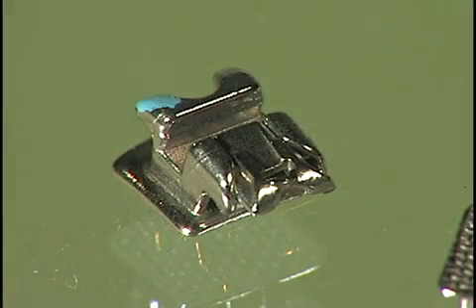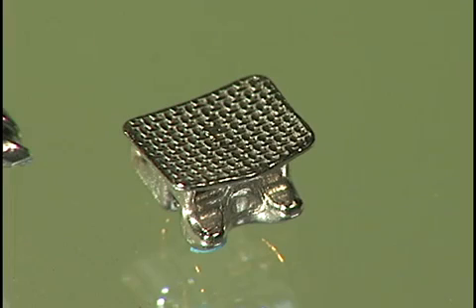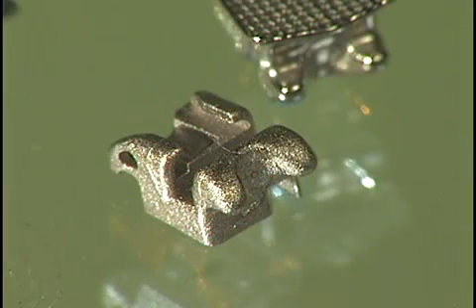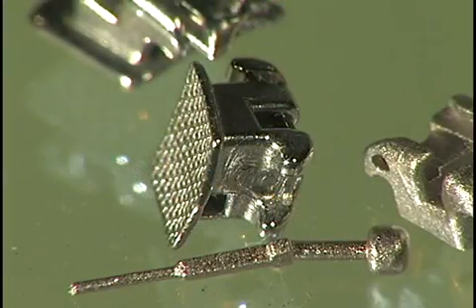The very tiny, intricate parts are made by metal injection molding from 17-4 PH stainless steel powder to a density of 7.5 grams per cubic centimeter. They have impressive physical properties: a tensile strength of 172,000 psi and a yield strength of 158,000 psi. All of the parts are made to a net shape. The customer tumble polishes them and performs a brazing operation before assembly.